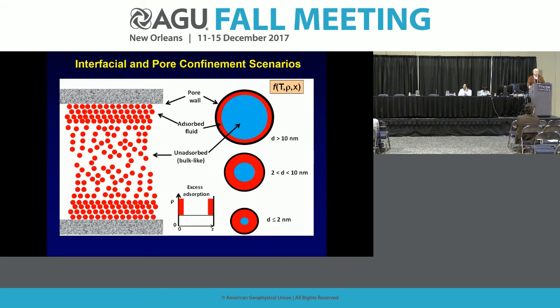So just to benchmark this for you, imagine now you're a pore, a slit pore or a circular pore, and you've got a fluid inside that's trying to react or behave in a certain way. Imagine you've got densification at a surface, maybe less dense out here in the center of the pore, and as pore size changes, you can get a sense that the adsorption layer, the interaction layer, starts to take on more of a meaningful impact as you reduce the dimensionality from, say, a 10 nanometer pore to a 2 nanometer pore. So again, the relative contribution of fluid behavior is going to scale depending on the size of those pores and the pore volume itself. I'm going to show you just a few vignettes of outcomes to give you a sense of what we're learning.